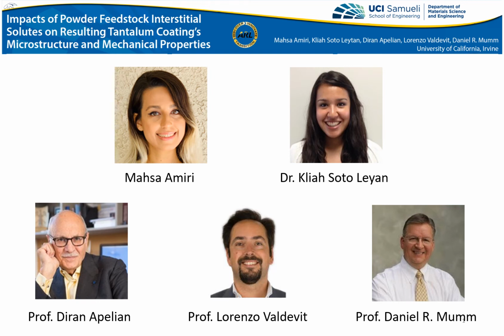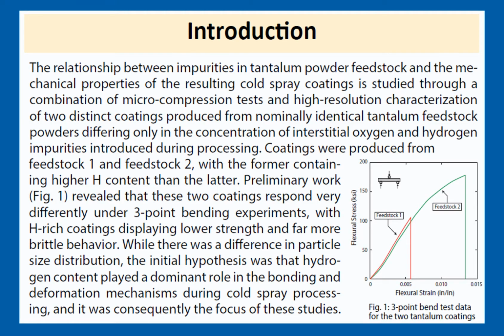The results you will see today are the work of a group of researchers at the University of California, Irvine. Our work is focused on the relationship between impurities in tantalum powder feedstock and the mechanical properties of the resulting cold spray coating. It was motivated by the differences in mechanical behavior of two different coatings produced from nominally identical tantalum feedstock powders, differing only in the concentration of interstitial oxygen and hydrogen impurities introduced during processing.